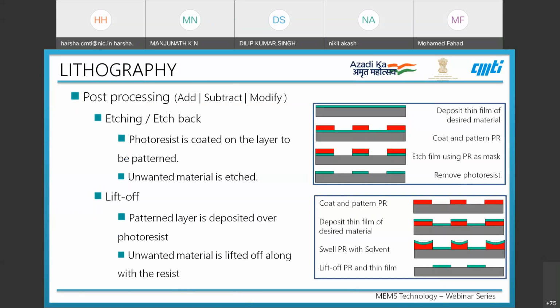In etching or etch back, the photoresist is coated onto the layer to be patterned, and unwanted material is etched out as shown in the image. During liftoff, the pattern layer is deposited over the photoresist, and unwanted material is lifted off along with the resist during the development process.